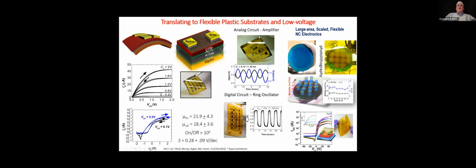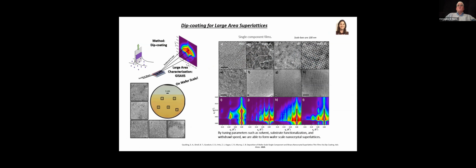These types of systems can be played out by depositing these nanocrystal films over wafers up to about 4 inches, and then you can really begin to start characterizing prevalence of defects, reliability, measuring the mobility of the devices or performance characteristics across many positions on the supports. It helps if we can take those artificial atoms from the nanoscale constituents and build them up to wafer size assemblies that then still retain some of the interesting tunability of the smaller components, then we're getting closer to our goals.